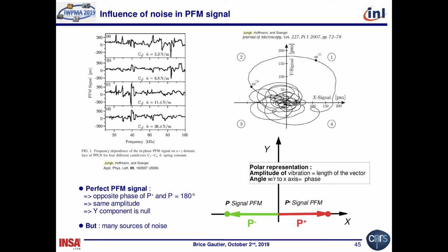This is the P plus signal, and this is the P minus signal in a polar representation. You have 0 degree, and you have 180 degree. And this is the perfect PFM signal where they are strictly opposite one to the other. If you just move the frequency of this kind of measurement, using this polar distribution, this is done by Jung, you see that you have any kind of result. So your signal can be anywhere in this polar plot. It can be there, it can be there,